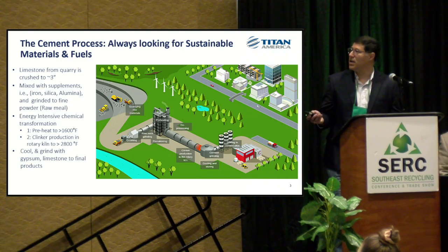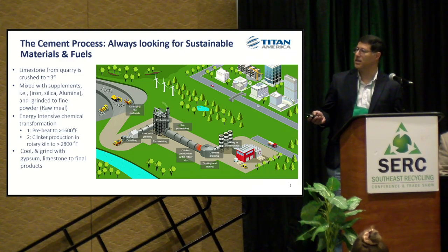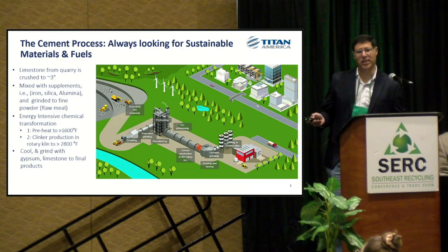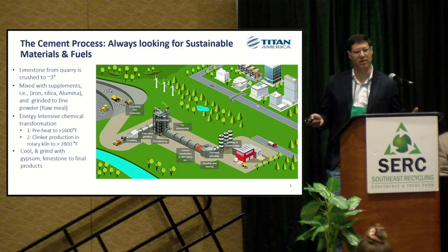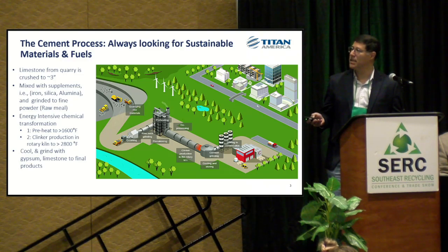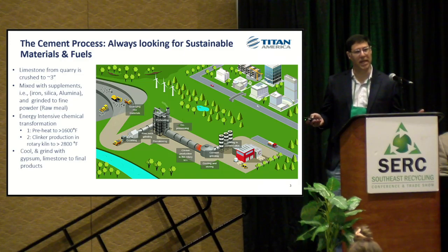Basically, the process starts with a quarry where we bring the limestone and crush it to 3 inches minus, into a system. Then we add some supplements like iron, silica, and alumina. And by the way, these supplements do not necessarily have to be virgin materials. We use fly ash, for example, roughly 250,000 tons per year from coal-fired plants, and we use copper slag as an iron source, and so on and so forth.